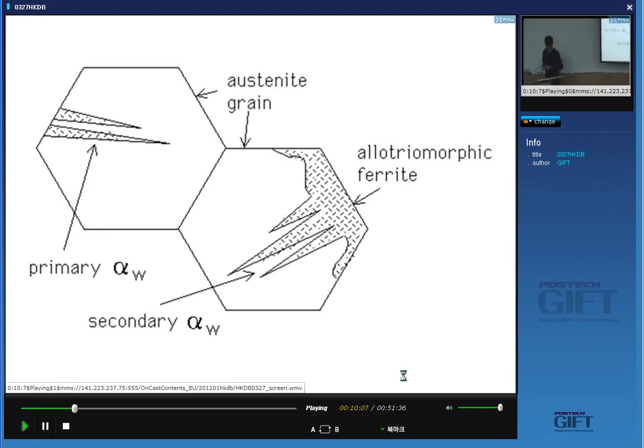The structure is drawn coarsely because if an austenite grain size is about 30–40 micrometers, the plates are growing roughly the size of the austenite grains. When we look at this in an optical microscope in a partially transformed condition, the Widmanstätten ferrite does not etch dark — it will appear white in optical micrographs. This is in contrast to bainite which etches very dark. So you can distinguish this easily from bainite and from untempered martensite from the way it etches.